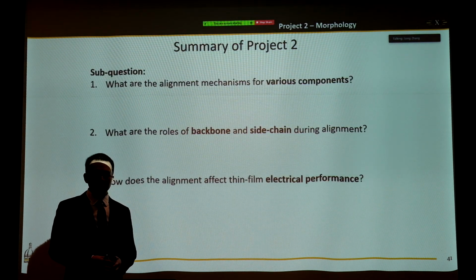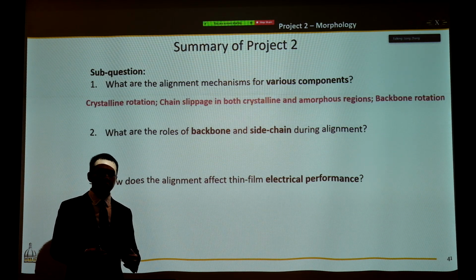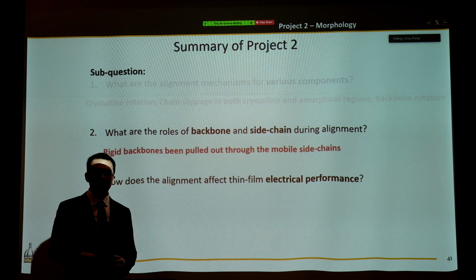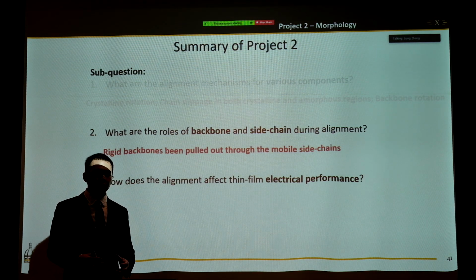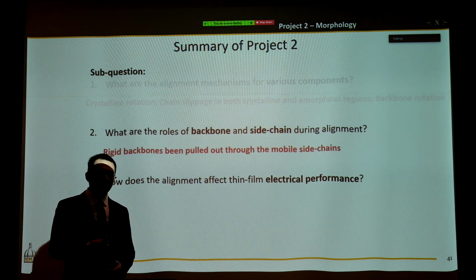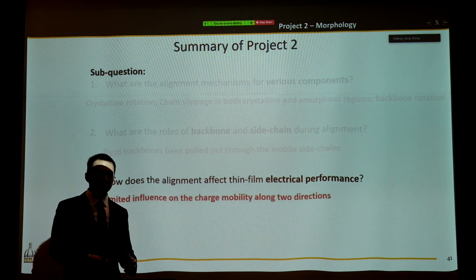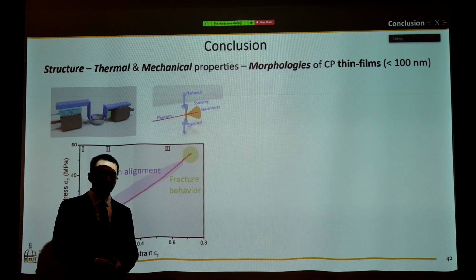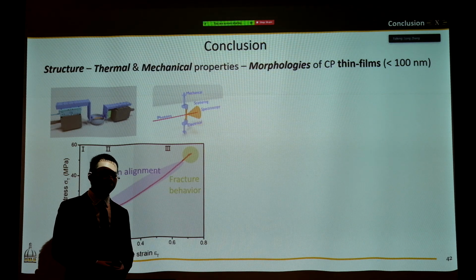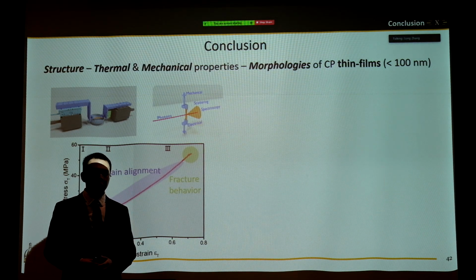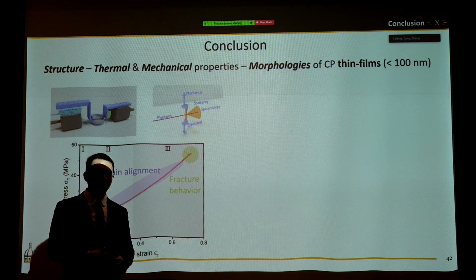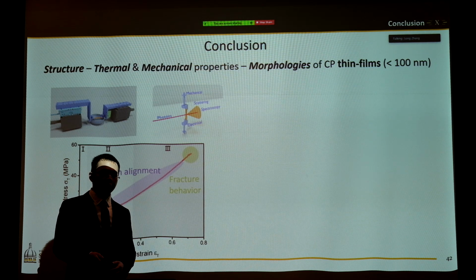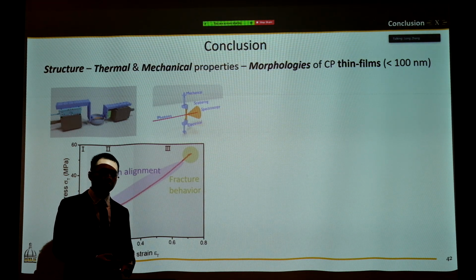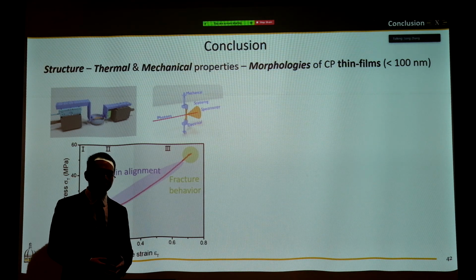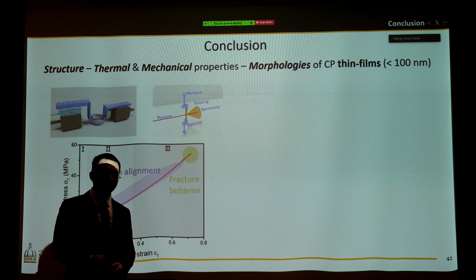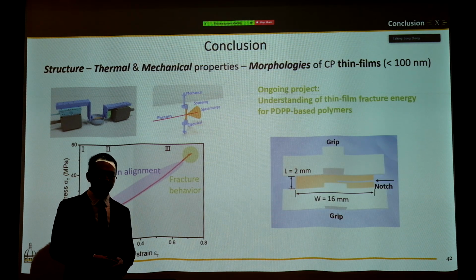So to summarize this project, we successfully identified different mechanisms for different components. We also disentangled the role of backbone and side chain on the crystalline orientation. We also identified the effect of the alignment mechanism on the thin film electrical performance. So in conclusion, I hope I showed you a coherent study on the structure, thermomechanical property, and electrical performance relationship for conjugated polymer thin films. We showed the linear region where Tg and elastic modulus play a very important role, the plastic region where chain alignment happens, and I also have an ongoing effort to understand the fracture behavior of these donor acceptor polymers.